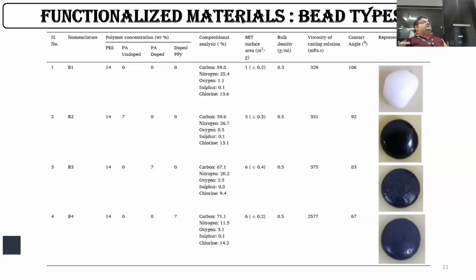We saw that the surface area, although comparatively very small, and the viscosity comparatively very high. But when it comes to polypyrrole beads, the hydrophilicity of the beads is extremely high, and it can be seen with the reducing contact angle that these are forming spherical structures.